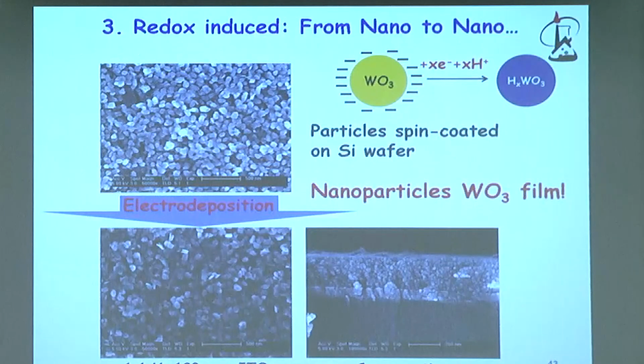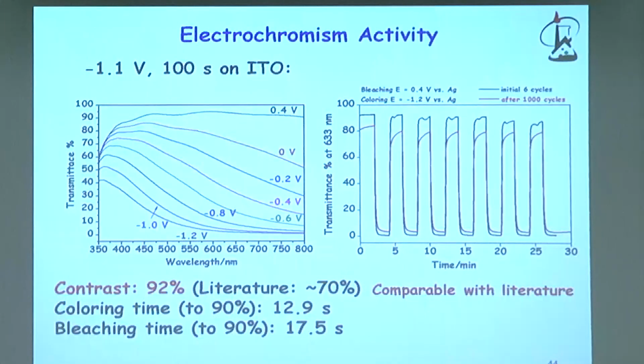So this is the actual nanoparticles, this is the film which is formed, and we show very nicely, and again, very shortly because of the time, that what we get is a film which is made of nanoparticles of tungsten oxide, and they actually behave very well. They have a very strong contrast, and the coloring and the bleaching time is very short as compared to continuous film of tungsten oxide. And the reason for that is their nanoparticular structure and nature that enables the ingress and egress of lithium ions going inside.